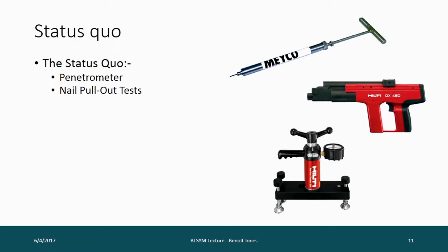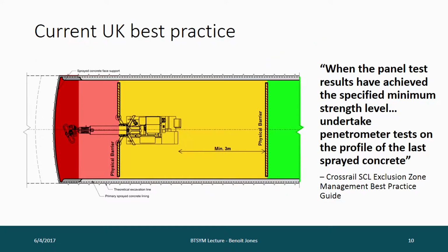So the status quo, how do we mitigate this risk? When we finish spraying the tunnel lining, we pull the machine back into the yellow zone or beyond, and we spray a panel, and then we do tests, usually penetrometer tests, and then possibly also Hilti tests in the panel to tell us what the strength is.